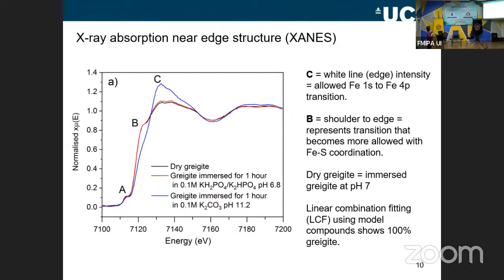So this is the kind of data that we get. The technique itself is called XANES, or X-ray absorption near edge structure. But the important thing that you have to notice is if you just look at the spectrum that is shown in black and the one that's shown in red, they both look exactly the same, basically. They're on top of each other. To interpret these spectra, we just need to look at some of the features. The important features to look at here are the feature that I've labeled B, which is this shoulder to the spectrum, and then these features up here, which are the higher intensity, labeled C. C is what's called the white line intensity, and this is the first allowed transition for iron. So it basically tells you that it's iron and what oxidation state it's in, its position.